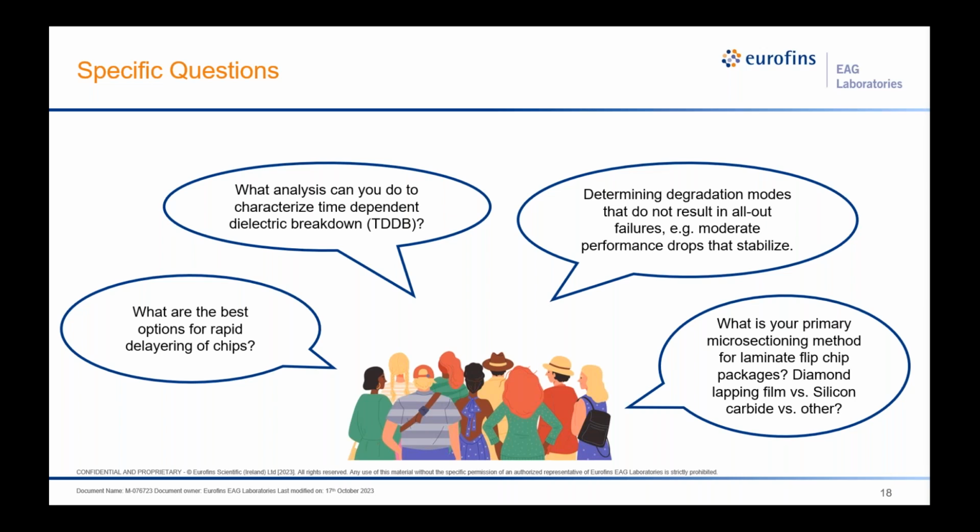The other factor would be how localized and pinpoint the site is that we're going after. Obviously the processing is a PFA, or physical failure analysis, technique. To be able to look at a very pinpoint site, let's say one isolated with infrared microscopy or OBIRCH, then we have a very specific location to deprocess and look for the physical damage or